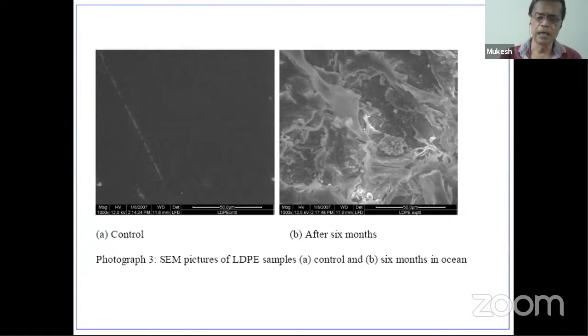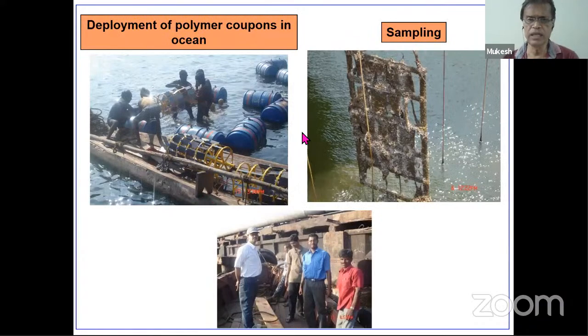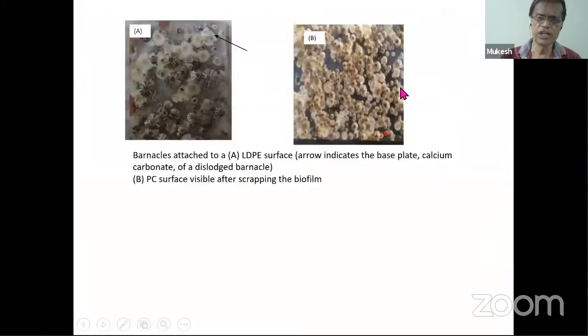Because when you place polymers in the sea, there are a lot of ocean currents, which can lead to biodeterioration of the material, and you can see barnacles present on the polymer. A large number of barnacles. This is the biofouled polymer after removing all the soft material. We can see the barnacles really attached. It's practically impossible for us to remove these barnacles unless we give an acid treatment of the surface.